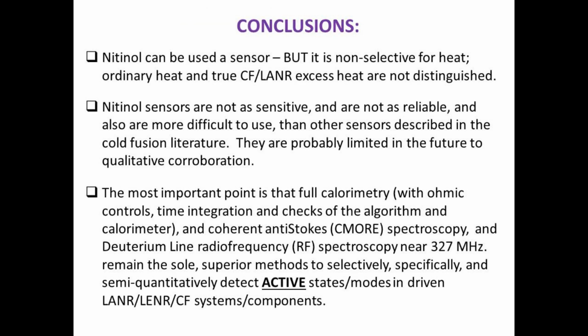In conclusion, nitinol can be a sensor in cold fusion, but it is non-selective for heat. Ordinary heat and real cold fusion excess heat are indistinguishable. Furthermore, the sensors of nitinol are not as sensitive or as reliable and are more difficult to use than other sensors described in our literature.